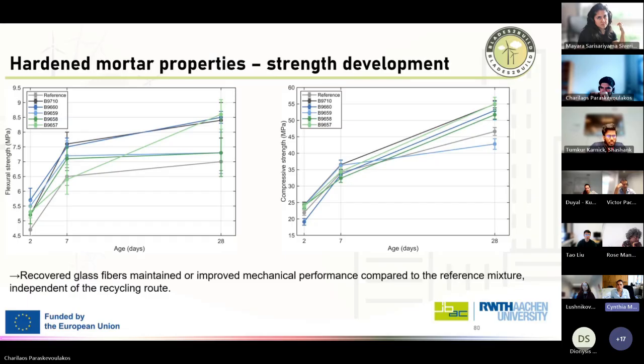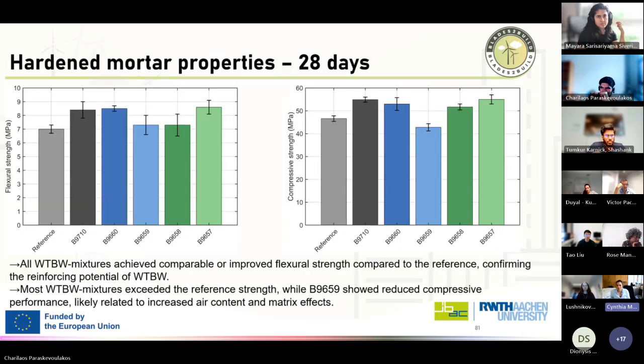So if we go to the next slide, I have picked out the data on the flexural and the compressive strength, which is just based on the 28 days. We actually did see all these values in the slide before this, but I think it's sometimes easier just to concentrate on one specific date. So we do see again here that we did improve our flexural strength with every addition of the wind turbine blade waste.